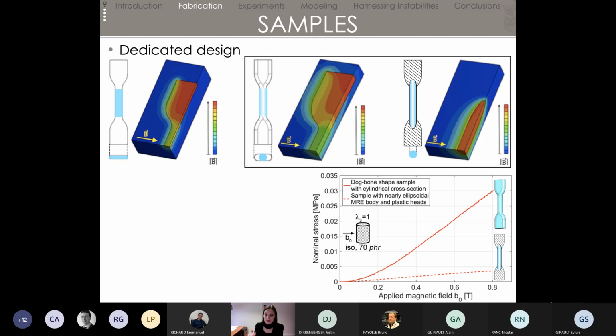So now we take those two last samples and put them under magnetic field. And what we do is that we maintain their displacement, so we see how much force they exert on the setup. So the solid line in red, it's the sample with the magnetorheological elastomer heads. And you can see it develops much more force than the one that doesn't have magnetic heads. Which means here that the heads of the sample would contribute to the response of the sample if they were magnetic, in which case you would not be doing material characterization. So if we want to do magnetomechanical characterization, we have to use this third sample.